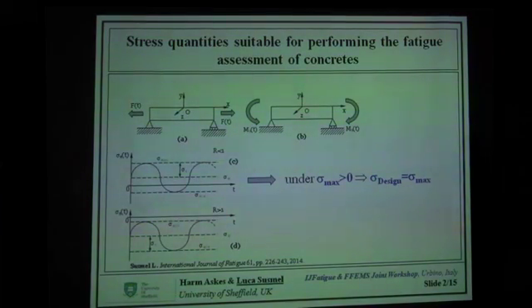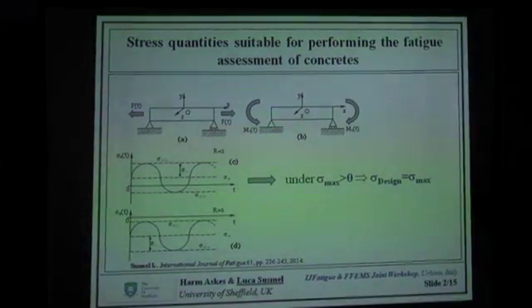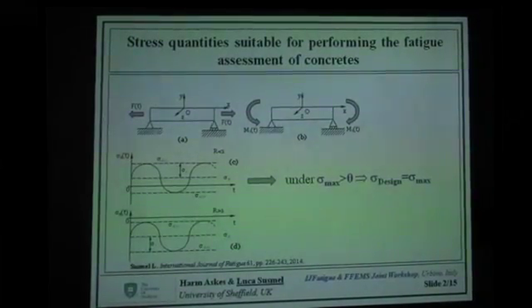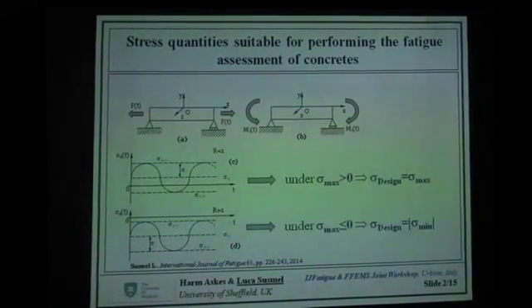By analyzing a large number of experimental data, we have observed that we can simply use the extreme stress in the cycle to perform the fatigue assessment of concretes. In particular, when the load ratio is lower than 1, that is when sigma max is larger than 0, sigma max, the maximum stress in the cycle, can be used as the design stress to estimate fatigue lifetime. But when your concrete works under cyclic compression, basically you get the mirror situation. So the absolute value of the minimum stress in the cycle can be used as a design parameter.